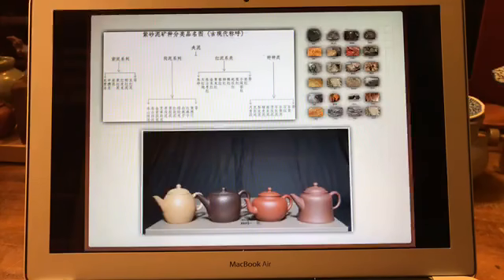The bulk combination of different strata of clay to give a consistent clay material is important for mass production. That's because you won't want a clay material that is a different strata every day, and then the firing temperature is different, right? The firing properties and shrinkage are different. That would be a nightmare for consistency.